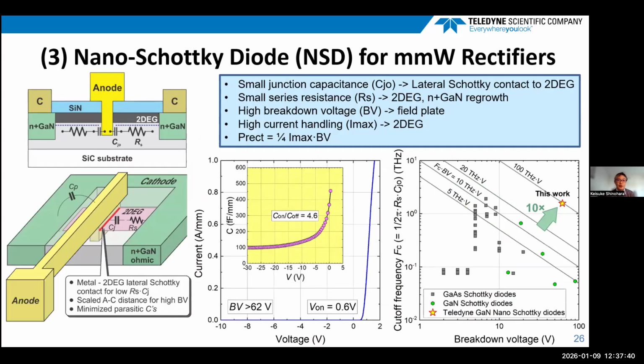Next, I'll talk about the nano-Schottky diode designed for millimeter wave rectifiers. In this structure, we use a lateral metal contact to the 2DEG. This structure enables us to minimize the junction capacitance because, like I said, the 2DEG is confined within 1 to 2 nanometers, so the contact area size can be minimized. At the same time, the high electron mobility and high density of 2DEG minimize the series resistance. And we used an n+ GaN regrowth process to minimize the parasitic resistance associated with ohmic contact.